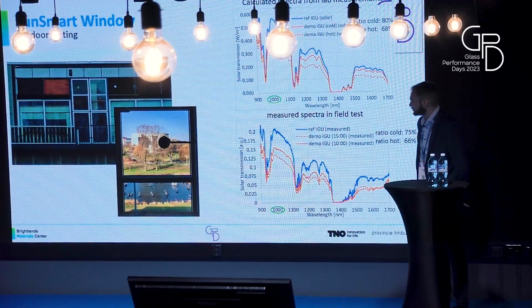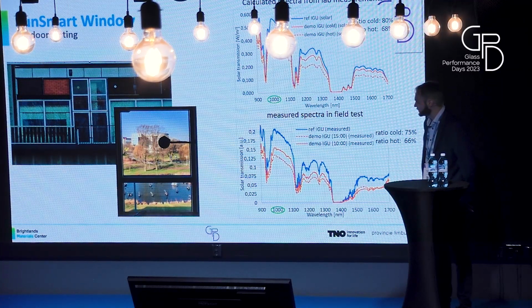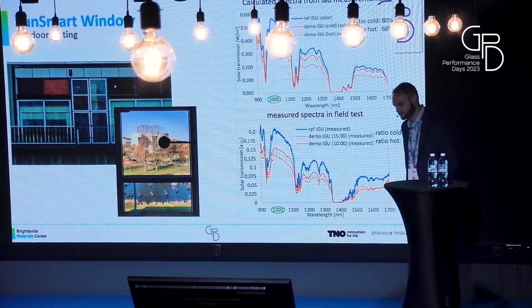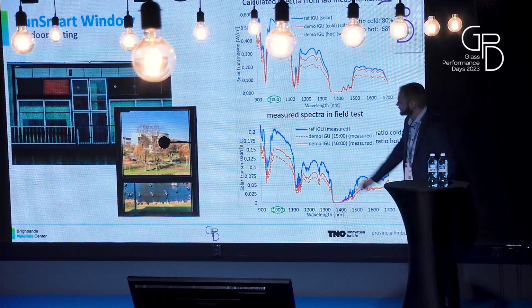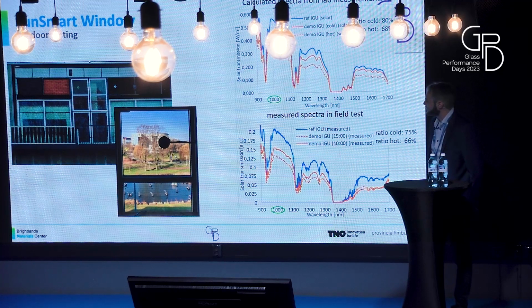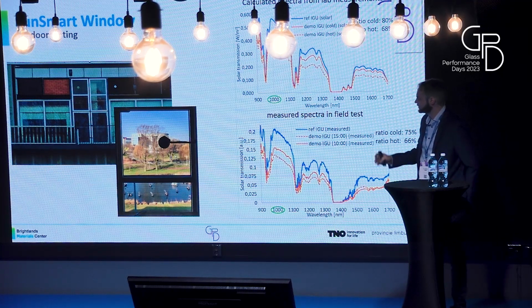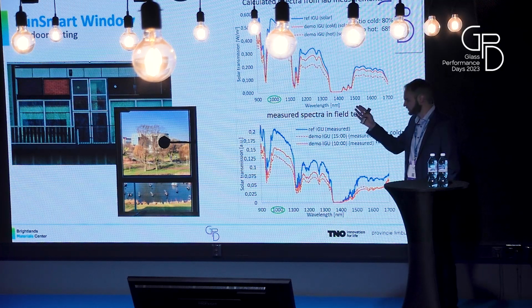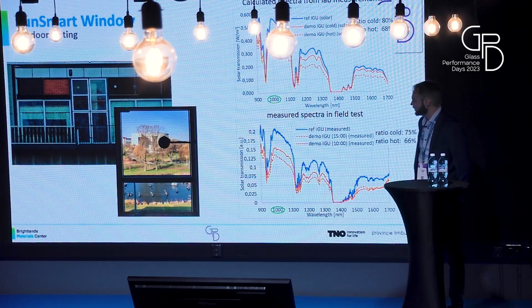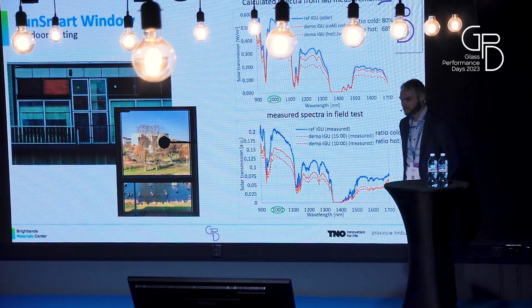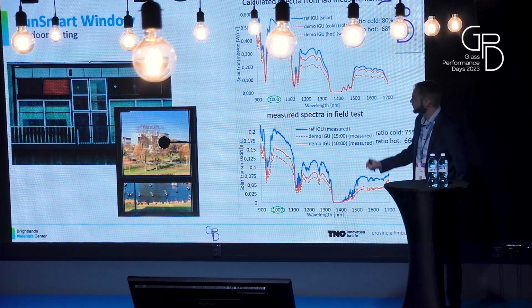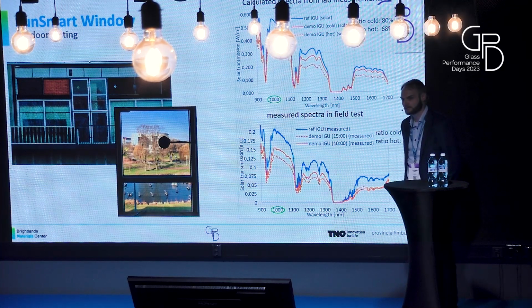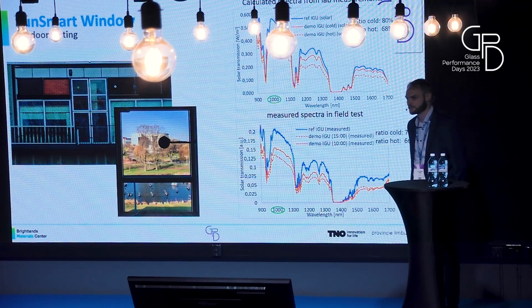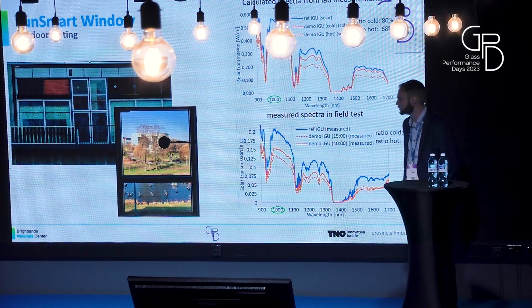What we also have done is produce a demonstrator of 1 square meter size and test it in a real environment in the Netherlands. This is an installation in Eindhoven on the west facade. What we did there is integrate temperature sensors into the laminate. This is also based on laminated glass. We laminated temperature sensors into the glass so that we can monitor the temperature of the glass over a year. And we have a sensor behind the glass so that we can also monitor the transmission in the visible, but also in the infrared, so that we can actually see how the material behaves in a real environment.